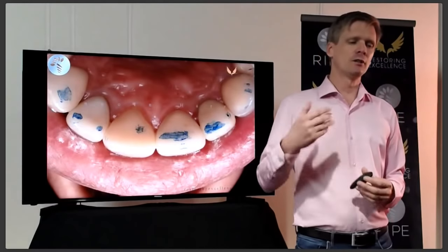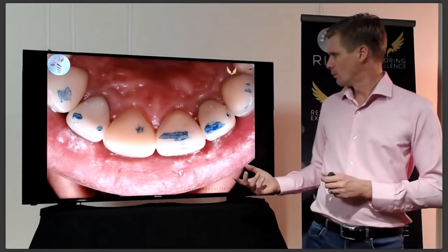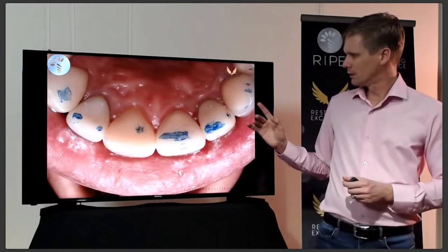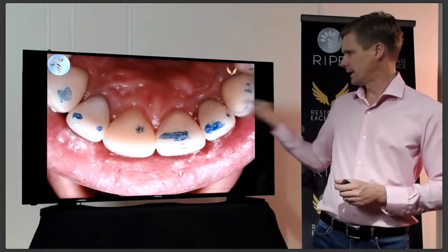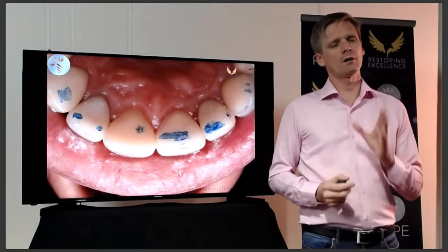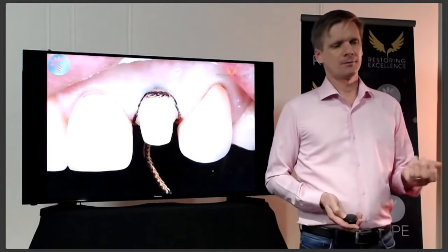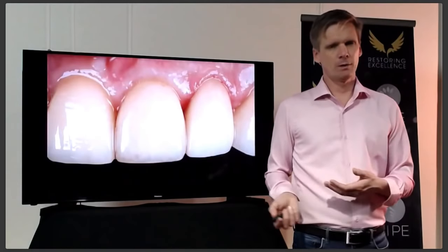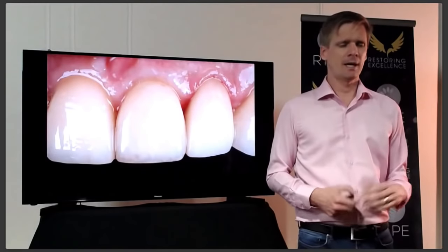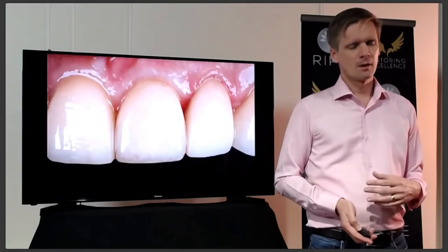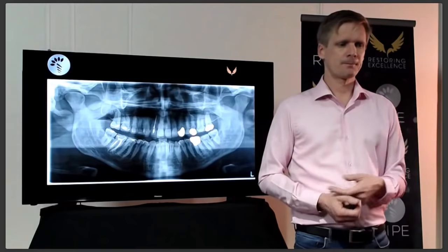But it's interesting when you look at this, because if you look at where the lower teeth are hitting, one of those curved, rotated lateral incisors on the lower is hitting right there, okay? Right on the crack. So we replaced that one, and it was replaced with full contour Emax. It's just stained and glazed. And so this case is now 12 years old.